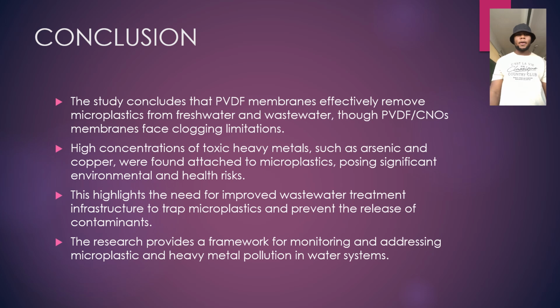To conclude, this research highlighted the importance and the need for advanced water treatment solutions to address microplastic and heavy metal contamination. Using modified PVDF membrane, the research successfully removed both pollutants, demonstrating the potential of membrane filtration to enhance current wastewater treatment systems. The presence of toxic metals like arsenic and copper on microplastics underscores the risk these pollutants pose to the ecosystem and human health.